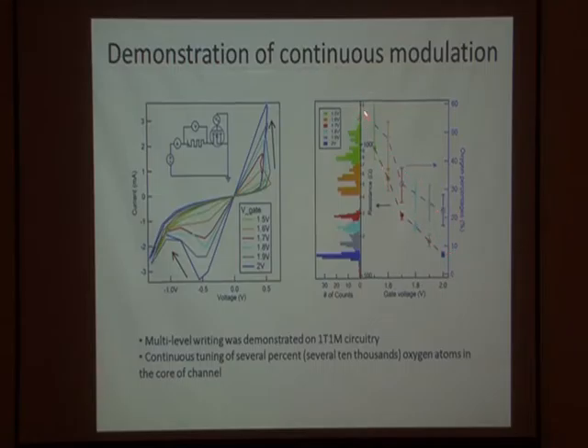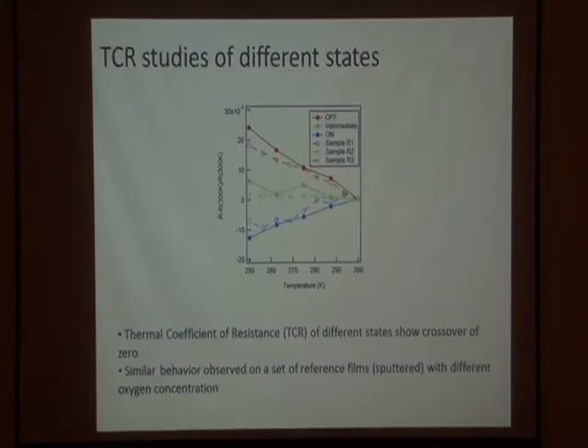So this is what we get, and this is the oxygen percentage that we get inside the channel. It can vary from say 20 to 50%. The way we did that was by measuring the temperature coefficient of resistance. It's a unique relationship between a composition and this number here. So I invite you to take a closer look at the paper, published in ACS Nano. The cool thing is that you see a metal to insulator transition. As you go deeper and deeper into this, if you're into transport, the term that describes the system best is Fermi glass, as defined by Mott.